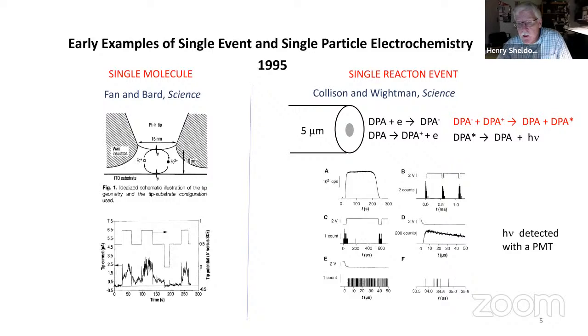And the experiment is to take a small microelectrode, a gold wire, and reduce diphenylanthracene to make the radical anion. And then you switch the potential quickly and you oxidize some DPA to make the radical cation, all at the electrode surface. And then the anion and the cation annihilate each other to make a ground state DPA and an excited state molecule. The excited state immediately, within a microsecond, returns to the ground state and emits a photon.